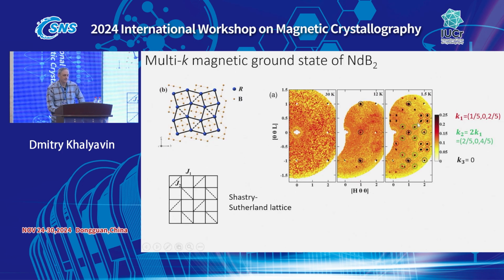And I asked, did you measure this in a magnetic field? Because the second harmonic has to be non-magnetic, as we discussed above. It's a requirement, a very fundamental symmetry requirement, and it should not be here. But that's the spin flip channel. It's magnetic. Only magnetic scattering can go here. And he said, no, it's in zero field. And I was really puzzled how it's possible.